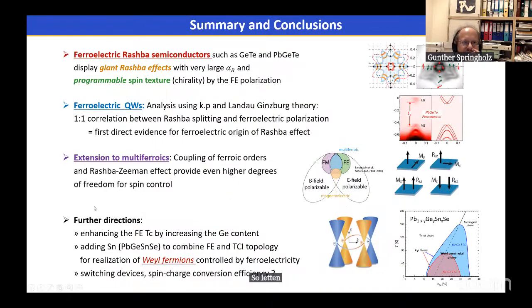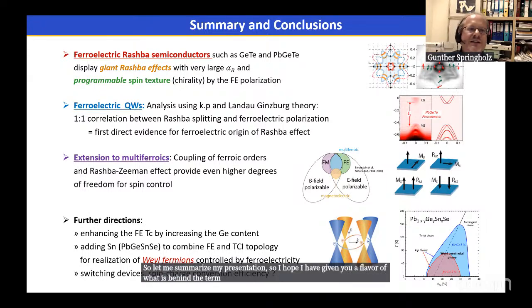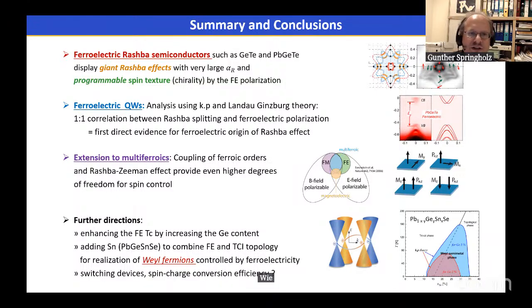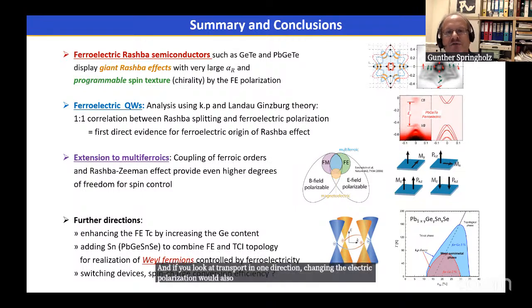So let me summarize my presentation. I hope I have given you a flavor of what is behind the term ferroelectric Rashba semiconductors. The basic essence is that due to ferroelectricity, this material can display a giant Rashba effect with very large Rashba constant. The spin texture can be programmed by the ferroelectric polarization, so you can switch by the ferroelectricity the chirality of the spin texture. And if you look at transport in one direction, changing the ferroelectric polarization would also flip the spin polarization of the current.